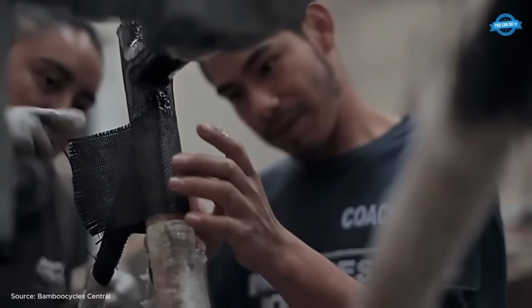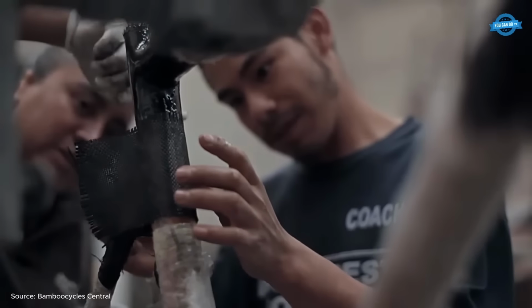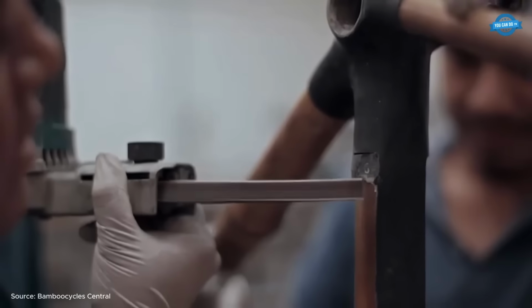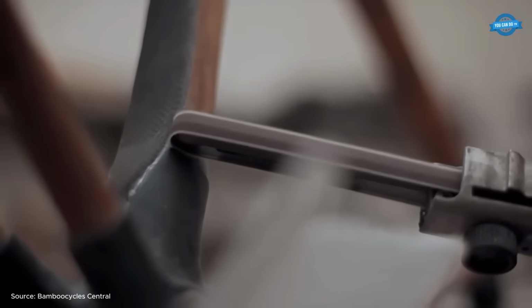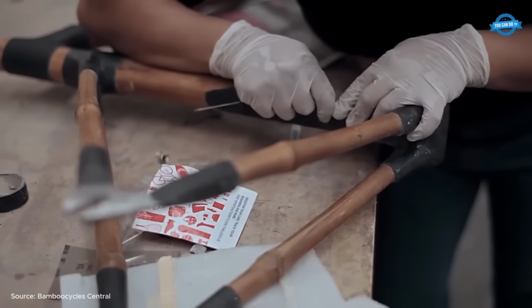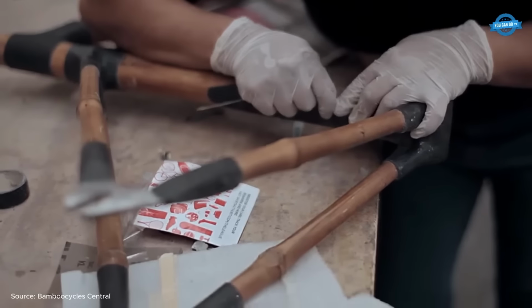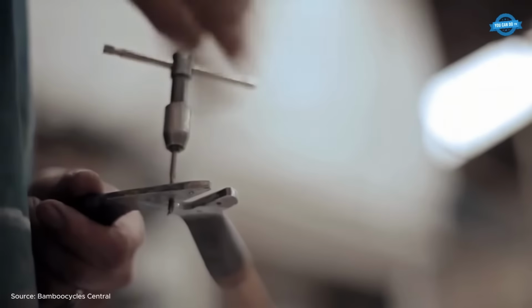On the second day, the real structural reinforcement begins. The joints are wrapped with unidirectional 50K carbon fiber soaked in epoxy resin. This multi-layer carbon fiber wrapping is the key technical step. By orienting 50,000 filaments per strand precisely around the intersections, the process creates extremely strong and lightweight lugs that bond the bamboo tubes into a cohesive, high load-bearing structure.